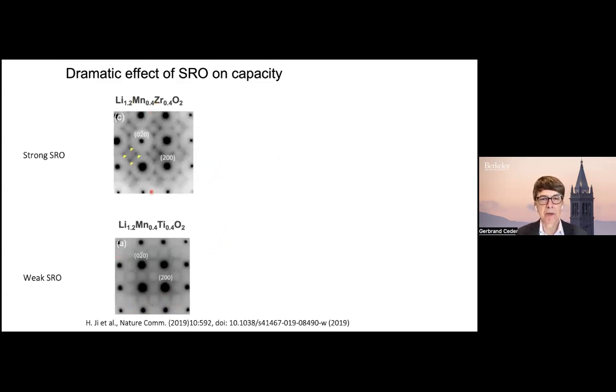Here's two DRX materials that are almost exactly the same. So the active redox species here is manganese. Zirconium and titanium are just 4+ stabilizers, as we call them. They're actually elements with no d electrons. So fully stripped d electrons tend to enhance disorder. But if you look at these, the materials were prepared in exactly the same way. They have very different short-range order.